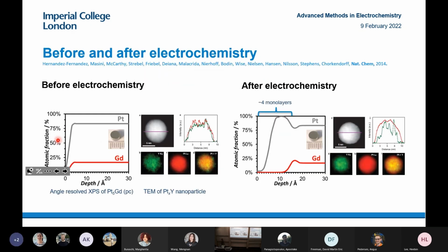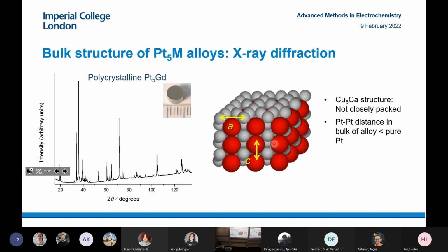So anyway, when we actually did the electrochemistry, we did a characterization both using angle resolved X-ray photoelectron spectroscopy and using TEM, getting an elemental map, before and after electrochemistry. Before electrochemistry, we see the rare earth right by the surface, and after electrochemistry, we see a really thick layer of platinum. So there's no rare earth in the vicinity of the surface, suggesting that we actually had a strain effect, and we really couldn't explain this. This was perplexing for us. And then when we tried to look, we thought about these kind of platinum 5 structures, because you imagine probably you have a strain effect.